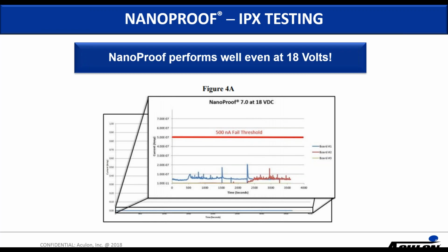So you can see here, for example, this is an example of our 7.0 material, which is expected to get IPX7 levels of performance. This has been coated. The board has been powered up at 18 volts. And you can see here over the course of 3,500 seconds, the current leakage was measured.